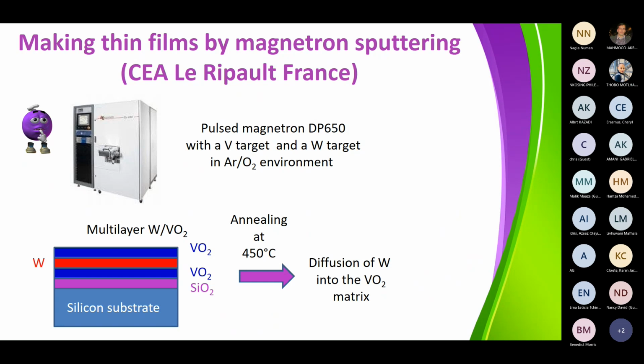And how did they manage to make the doping? By making multilayers. So they were depositing vanadium in oxygen atmosphere, so that this was transforming into vanadium oxide, and then tungsten, and then vanadium, and so on.